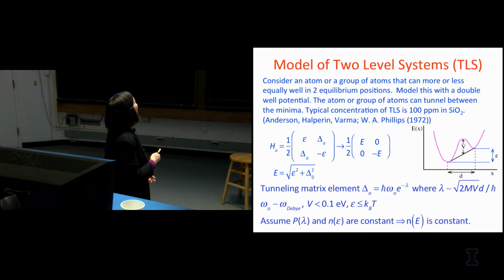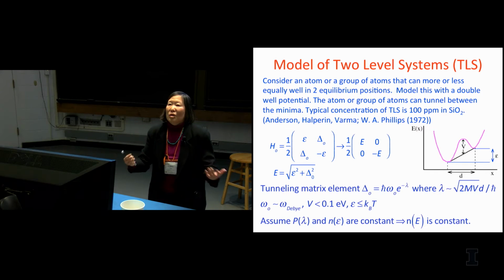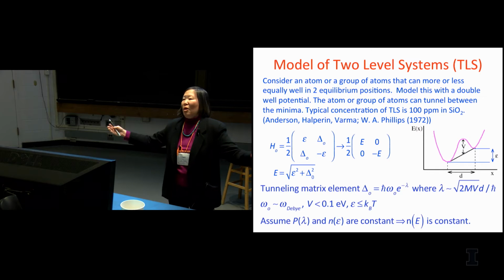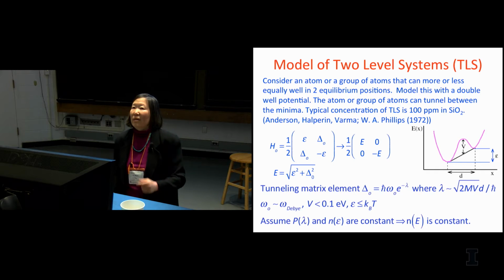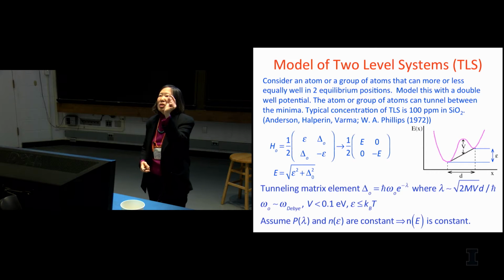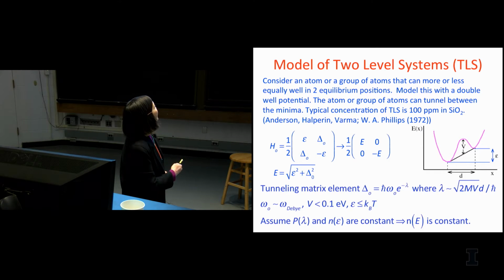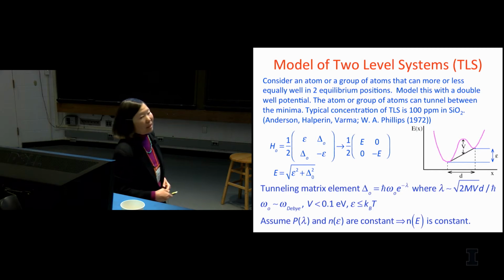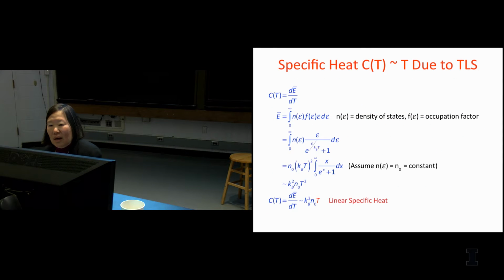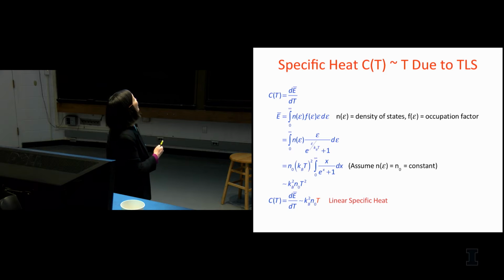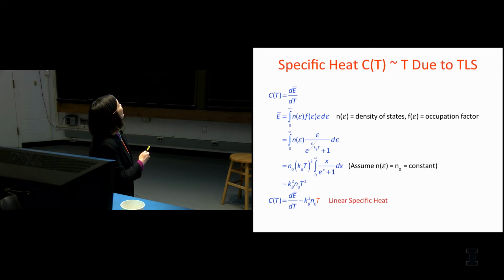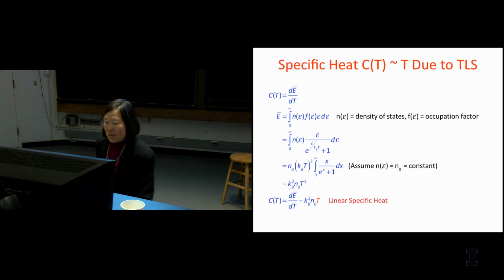And then the assumptions were that the distribution of exponents is flat, and the distribution of these asymmetry energies is flat. And the idea is, of course, it's not really flat. It's probably some Gaussian spread over some energy scale, hundreds of degrees Debye or whatever. But you're just looking at 1 degree. And over that small a temperature range, you could probably take a flat distribution. So then the energy eigenvalues would also be constant with this assumption. So then this very easily gives you a linear specific heat. You just write the energy as a constant density of states, occupation factor, that's a Fermi function, the energy, and you take the derivative, you get a linear specific heat.